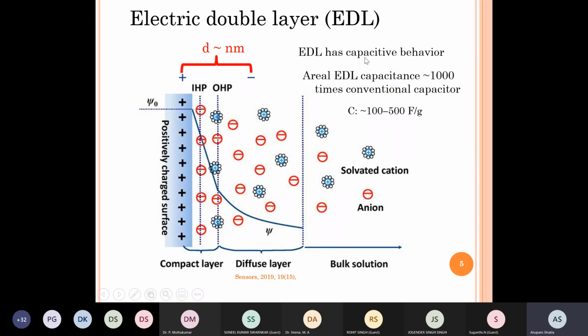So basically, the EDL will also show a capacitive behavior, except that the distance of separation between the charges will be at least 1,000 times smaller than in a dielectric capacitor. So by simple understanding, an EDL capacitance per unit surface area will be at least 1,000 times the capacitance that one can get in a solid state device. Of course, there are capacitors which are made on this principle, and they are called electric double layer capacitors, EDLC for short. Okay, and that is one type of supercapacitor. So that's how we get from capacitor to supercapacitor.